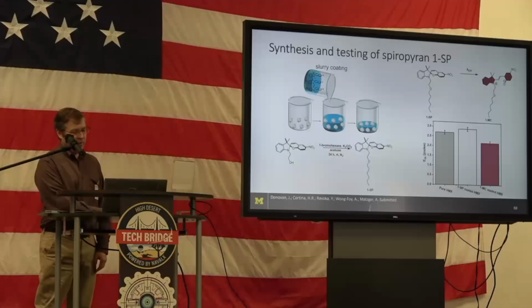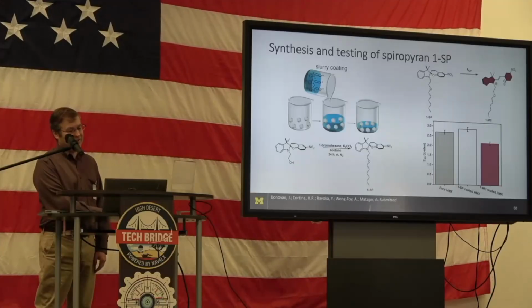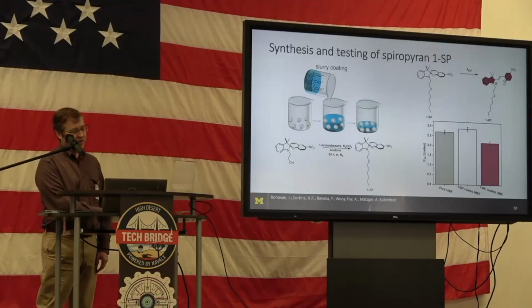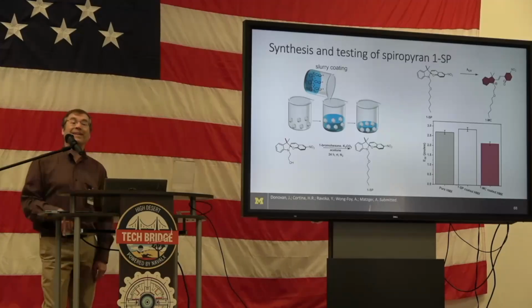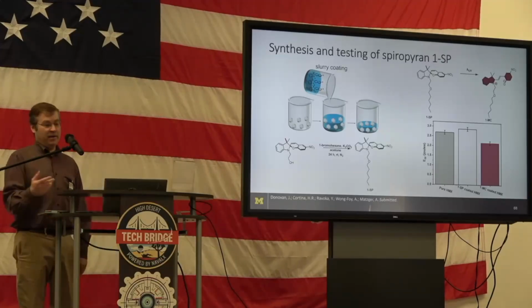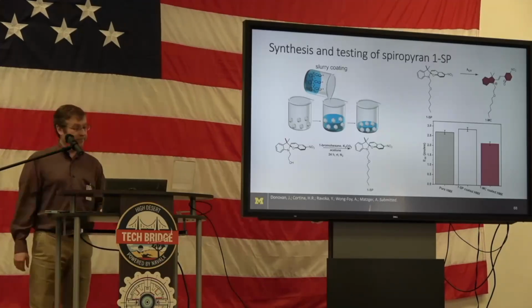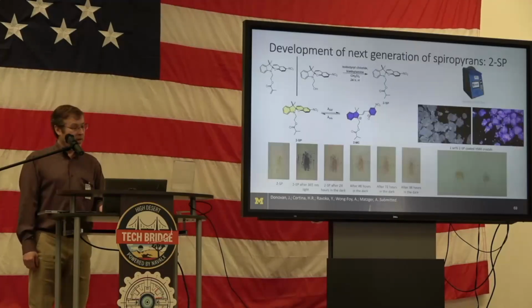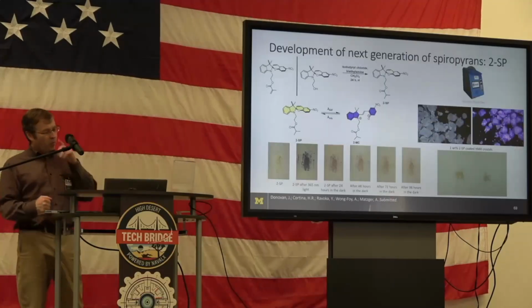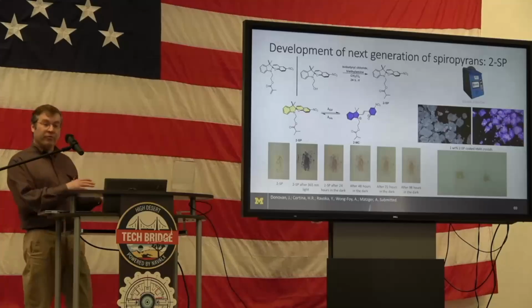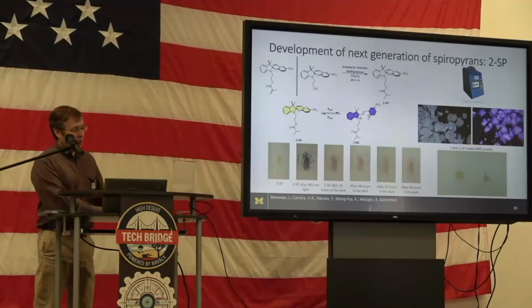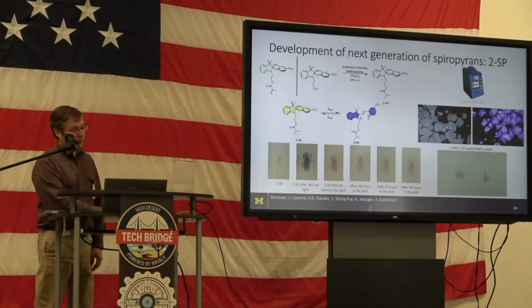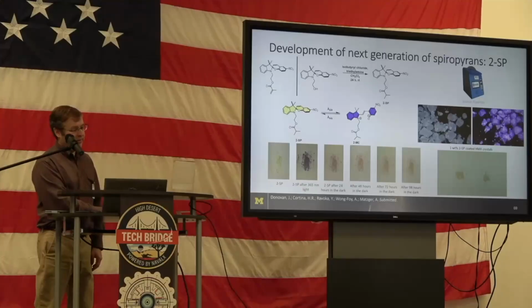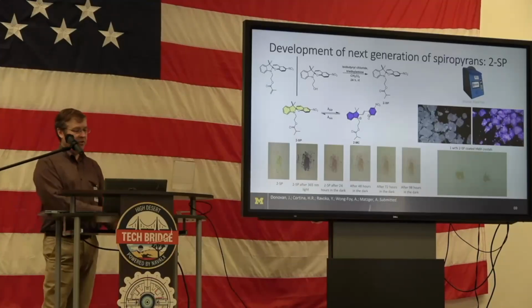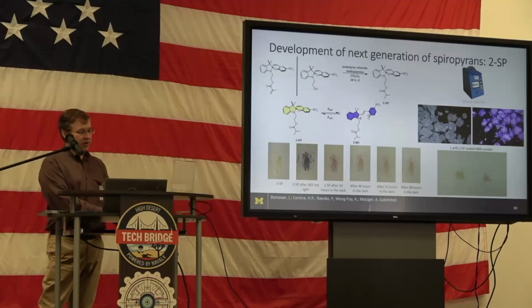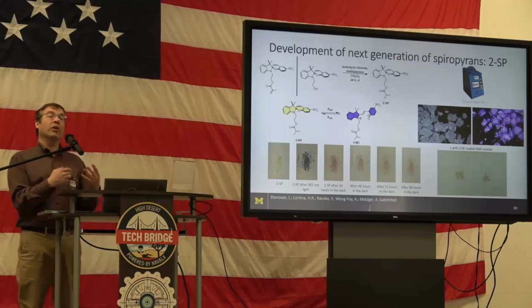We found that we could take HMX, desensitize it a little bit if we put some of this stuff on, and then sensitize it again by exposing it to light. We found that was not reversible in that system. So we found a system that was reversible, which is shown here. And you can see the reversibility. It will revert on its own.